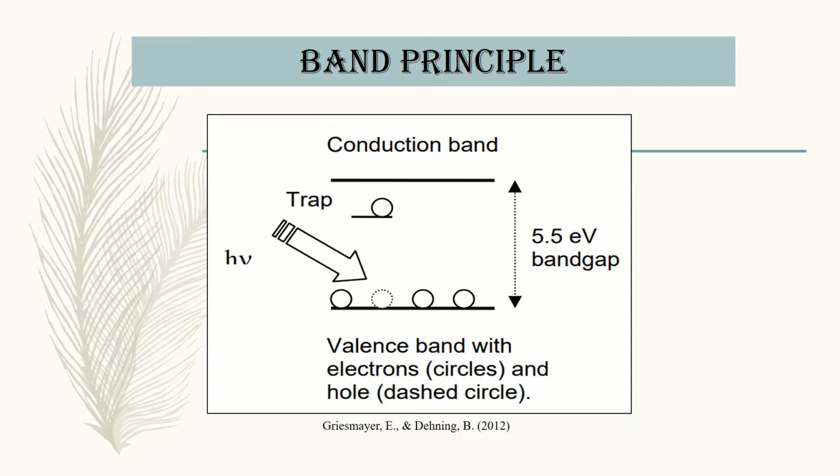Energy levels in between the valence and conduction bands are forbidden unless the lattice has been distorted by either impurities or dislocations. These sites can act as traps for electrons or holes, because they are immobilized here for a relatively long period of time. At shallow traps, electrons or holes may jump easily from the trap sites to the conduction or valence band by excitation or de-excitation of the particle.